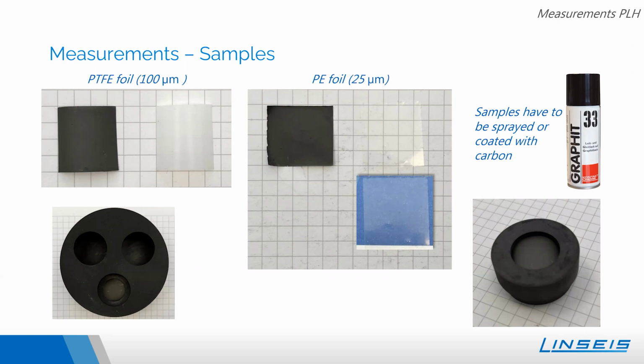On the top left is a coated and uncoated PTFE foil, polytetrafluoroethylene, or better known as Teflon. In this case, it's 100 micrometer thick, and it's pretty clear that it bends a little bit, but it doesn't matter because our sample holder will bend them down. In the middle of this picture, you see a 25 micrometer polyethylene foil, PE. As you see, one is coated and one is uncoated, but the uncoated one on the top is barely visible because it's so thin. And that's why I put it on a blue background to see it a little bit better. So to imagine, the measurable samples are really, really thin.